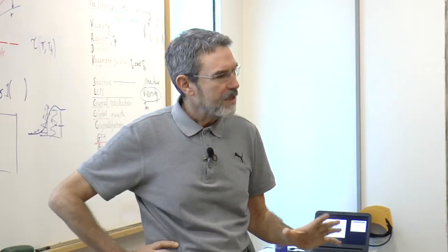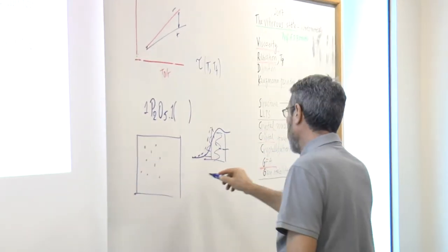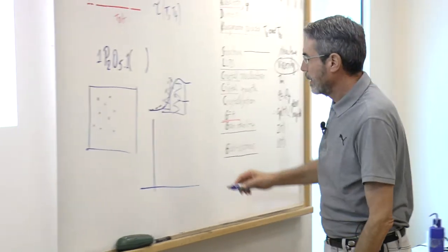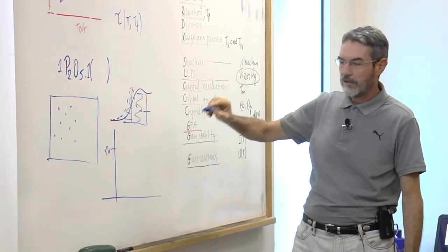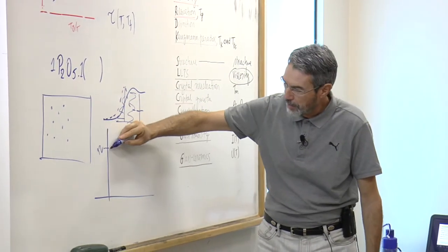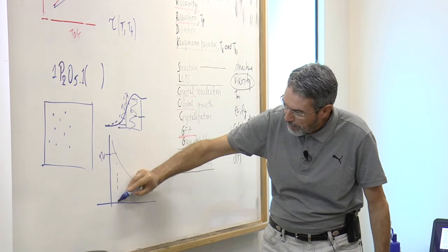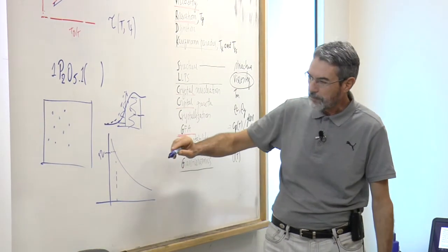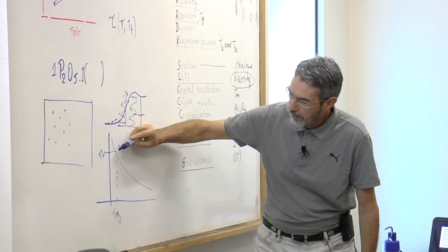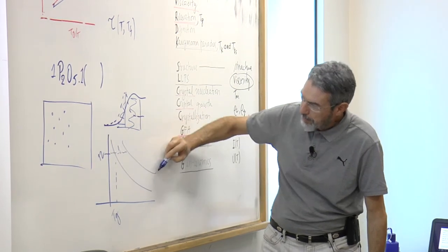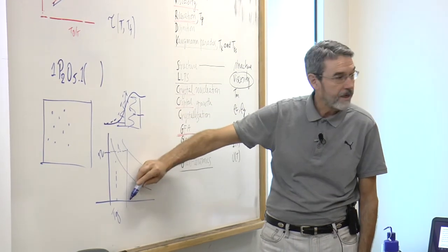But smaller TGs, in general, mean smaller viscosities, because you can plot a curve here. This is TG, 10 to the 12 Pascal second. If this is log of viscosity, so for this glass, the TG is here. So this is the TG of this glass. And for this glass here, the TG is here. So this has a higher viscosity and the TG is higher.